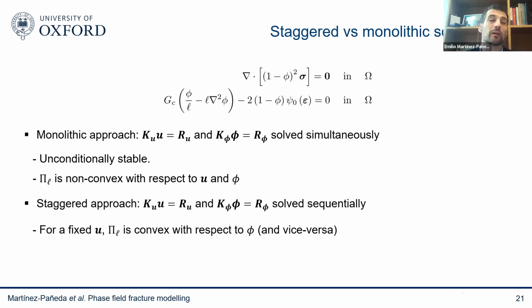So what a lot of the community is doing is what they call a staggered approach, where they first solve for the displacement, and then with the displacement field frozen, they solve for the phase field. So you solve one and then the other, basically. You solve them sequentially. This is also called segregated or staggered approach. And this is very good news because for a fixed displacement, the regularized functional is convex with respect to the phase field and vice versa.